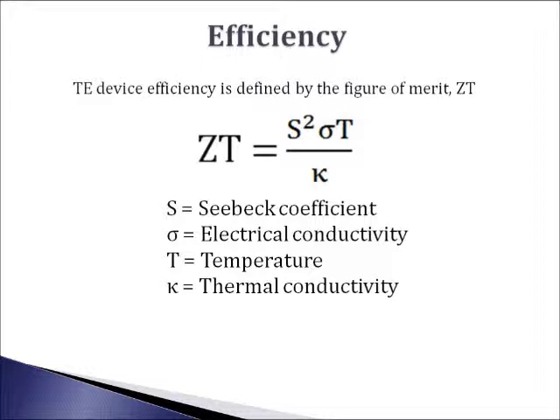ZT can be significantly enhanced by enhancing the Seebeck coefficient and electrical conductivity, and by reducing thermal conductivity. The Seebeck coefficient measures the magnitude of an induced thermoelectric voltage in response to a temperature difference across the material. Nanostructured materials have been proposed as a means to increase the Seebeck coefficient without increasing the thermal conductivity.